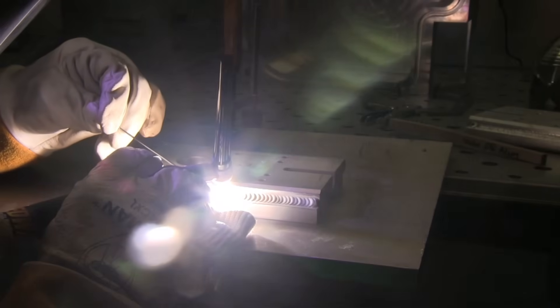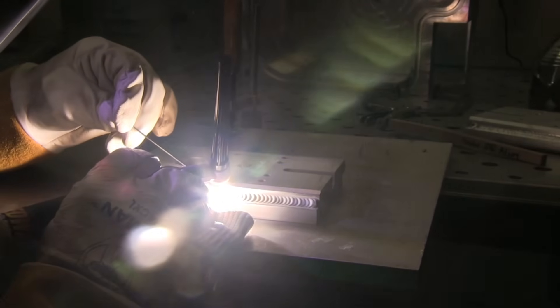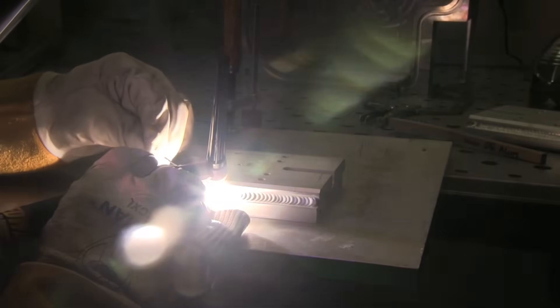The final weld is going to look better, but it's barely enough for that electrode to handle. This is a 3/32nd, 2.4 millimeter electrode, and it's quivering and balling. That's all the amperage it can handle is around 210 amps, at least on the current AC balance setting.